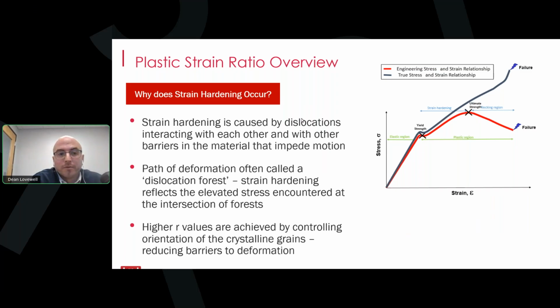This is why some alloys exhibit PLC, some don't, and some only do under specific conditions that lead to a PLC-affected microstructure. Now, one of the reasons why 5000 series alloys are really well suited for automotive structural applications is because their microstructure enables a lot of new dislocations to be generated during plastic flow. This enables them to be significantly strengthened during cold work. 6000 alloys, on the other hand, flow much more continuously.